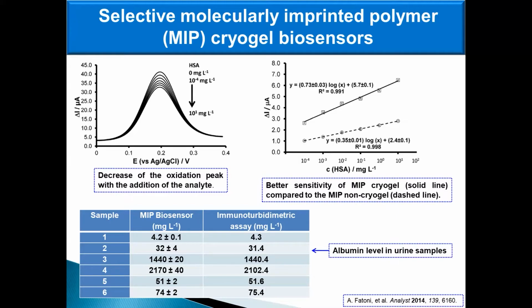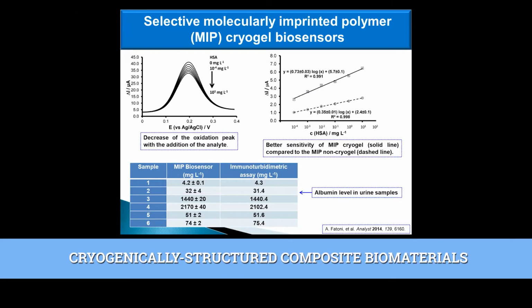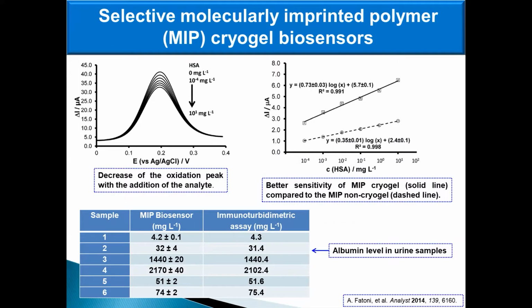For determination of albumin, the fabricated molecularly imprinted cryogel biosensor showed a high sensitivity with a wide linear range of 10⁻⁴ to 10 milligrams per liter and a low limit of detection of 5 × 10⁻⁵ milligrams per liter. The sensor was also used to measure the albumin concentration of 6 urine samples, and the results obtained were comparable to the standard method for detection.